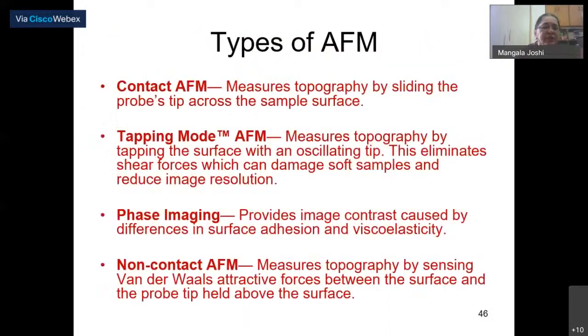Dr. Ashish. Yeah. So in the tapping mode, instead of a continuous contact, you have a tapping. So what you do is measure topography by tapping the surface with an oscillating tip. The tip is oscillating. That means it keeps going up and down, and this eliminates shear forces which can damage. So if your sample is very soft, or it can get distorted, and it can reduce the image resolution, then you use a tapping mode. Otherwise, if your material is strong and hard, you can use a contact mode.